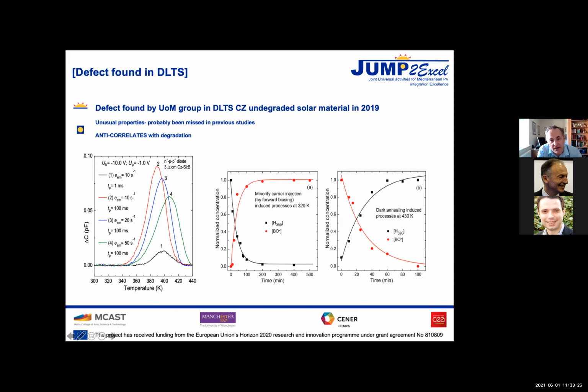It doesn't correlate with the degradation, it anti-correlates. So when we illuminate the sample, so going this way is illumination time, we find that this defect disappears and the degradation, the induced concentration, grows. So this is essentially a normalized density of defect states, of degrading states. We can measure that. It's extracted from minority carrier lifetime.